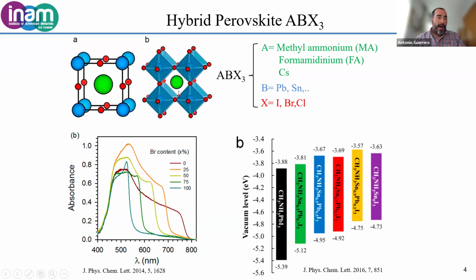And when we get everything right, then we get these 3D perovskite materials with this crystalline structure. And one of the reasons why the material has been used a lot over the last few years is because by slightly modifying A, B, or X, we can totally modify the optical properties, like in this case, where we have the methyl ammonium lead iodide perovskite in here, and we replace the iodide by bromide, we can totally tune and modify the absorption profile. But also the electronic properties change dramatically when one of these cations or anions are changed. And this is well known in the literature, but these valence band and conduction bands will determine how easy it is to extract the charge in the solar cell.